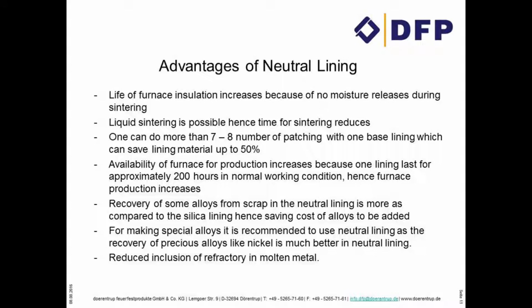One can do, say, one lining. Normally the acidic lining runs for a few heats, 18 to 20 or maximum 22 heats, whereas this lining runs for say 200 hours and around 70 to 80 heats. I am just giving an example, 70 to 80 heats. So you can run your furnace continuously. The availability of the furnace for production increases, and you can save on your sintering time and on your labor.